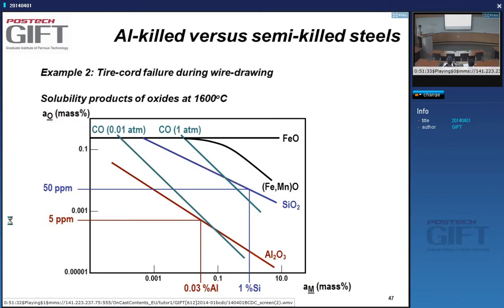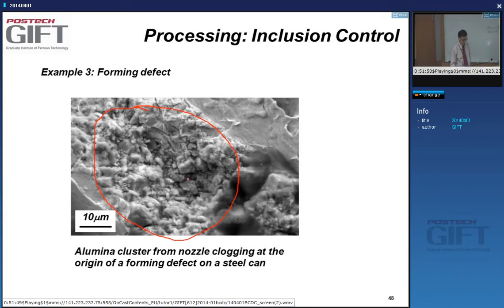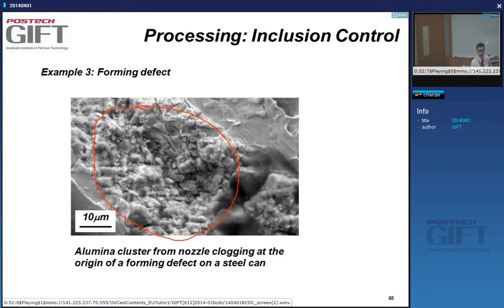Another example: forming defects in a deep-drawn steel can. The can has fractured and when the fracture is analyzed, a nozzle-clogging-type inclusion is found. Inclusions are very important when the steel has very small thickness or small diameter — one particle can destroy a wire because it's in the cross-section, or an alumina particle can cause early fatigue fracture of a spring. Another issue is related to MnS: a combination of banded microstructure and high aspect ratio inclusions — manganese sulfide is plastic and deforms very easily during rolling, giving very long, high-aspect-ratio inclusions that can cause lamellar tearing when you weld thick plates.